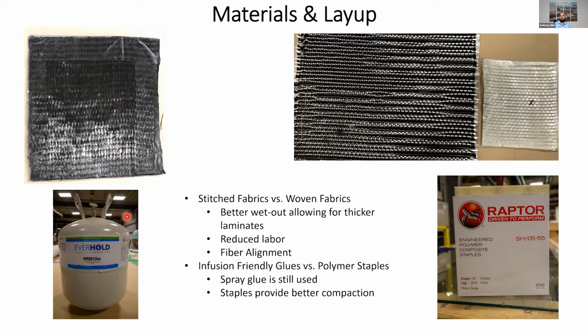However, we have minimized the use of these glues by also using polymer staples. Now these staples hold up better the layers of fabric to the foam core that we use in the webs, and that helps for a nicer or better compaction even before we put the vacuum bag on, and that leads to a better quality of infusion and also better looking radii.